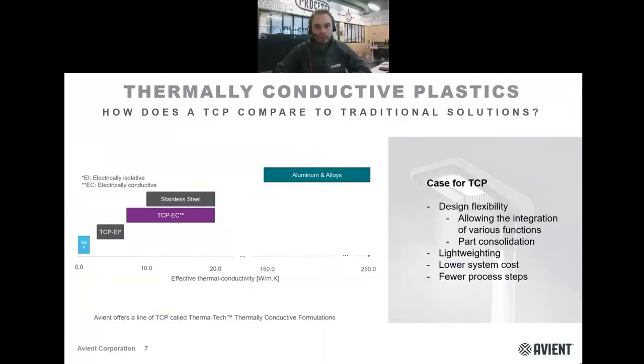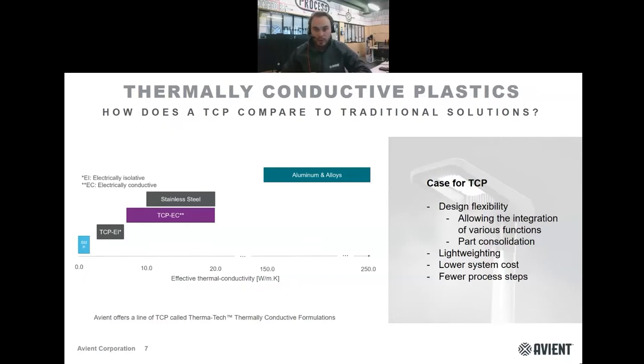Some of you may have always been told that to dissipate heat it is mandatory to use metallic heat sinks, but I can assure you that with a well-adapted design, thermally conductive plastics (TCPs) can do the job and offer many advantages in terms of design flexibility, weight and cost, despite the fact that their thermal conductivity is significantly lower than aluminum. While aluminum is around 150–200 watts per meter Kelvin, TCPs are between 15 and 20 — ten times less conductive than aluminum. However, a standard plastic has a conductivity below one, so ten times less conductive than our TCP solution.